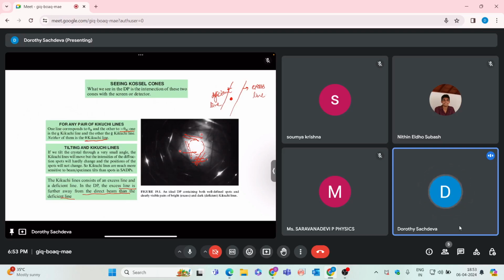Okay. So tilting and Kikuchi lines. I have already told you that if we tilt the crystal through a very small angle, the Kikuchi lines will move, but the intensities of the diffraction spots will hardly change, and the positions of the spots will not change. So Kikuchi lines are much more sensitive to beam specimen tilts than spots in the diffraction pattern. So for the tilting of your specimen, you always require your Kikuchi lines because these are very sensitive. These are basically just the road maps.